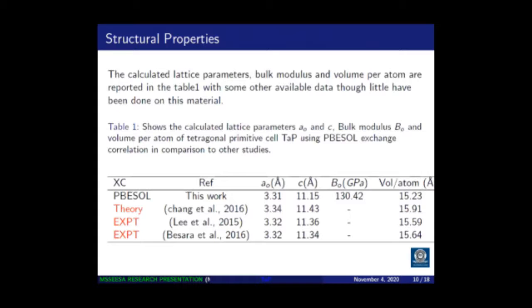Can you move to the next? So I also computed other structural properties like the lattice parameters, bulk modulus, and also volume per atom. And in this particular table, as you can see, I was able to get the lattice parameters. Like for a, I got 3.31. And if I compare with other studies, like Chang et al. got 3.34, Lee et al. got 3.32, and Besara et al. got 3.32. For the value of c, I was able to get 11.15. And you can see what other studies got: 11.43 for Chang et al., 11.36 for Lee et al., and 11.34 for Besara et al.